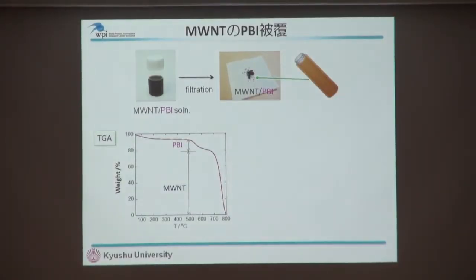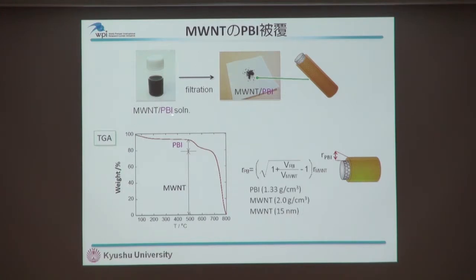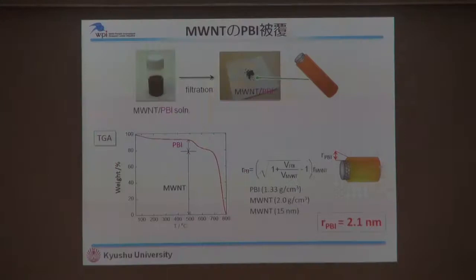So first, we measured the multiwall carbon nanotube PBI solution, and by filtration, we can make a solid like this. And by a TGA calculation, we evaluated the thickness of the polymer layer as 2.1 nanometer. That indicates that the polymer is very thin, just like a monolayer of the polymer coated onto the carbon nanotube surface.